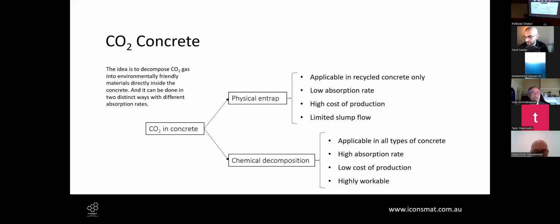Normally what we use here in the laboratories on construction sites are 10 mil aggregates and 20 mil recycled aggregates. So correct me if I'm wrong. I have to get the D10, D30, D60 of these recycled aggregates and then compare it with the standards, based on the upper limit and lower limit of the standards. Then I will be able to use it. Am I right or wrong? That's true, that's exactly right.